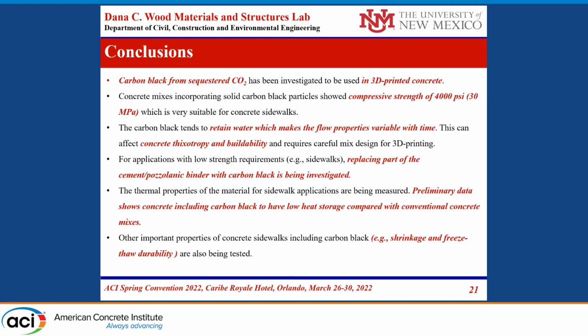One of the challenges we've seen is that the carbon black tends to retain water, and when the material retains water in 3D printing, then the thixotropy of the material will change as you are printing, and the material printability will change. So we are handling this with admixtures, but we are doing more research and work on addressing this issue, changing the mix so that it would be able to handle this amount of carbon black.